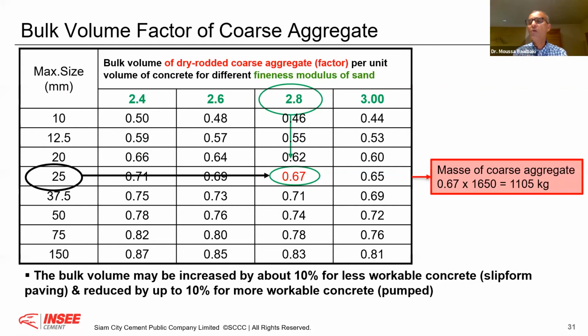Therefore, we now know how to get the amount of coarse aggregate. You have to keep in mind that if you have to pump concrete, you very often have to reduce the coarse aggregate by 10%, or if you have a slip form, you increase it by 10%. Therefore, there is also some recommendation in the standards, and also by practice we know that.